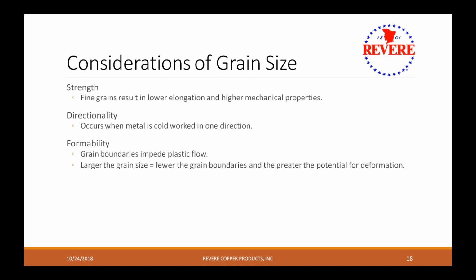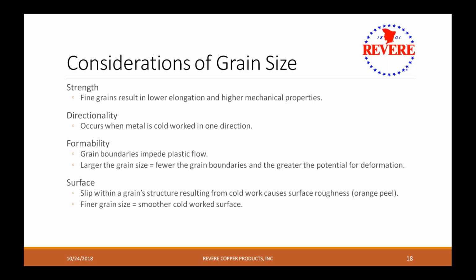And then finally, surface. So there's a condition called orange peel, and if you do a lot of cold work to metal prior to annealing, and then you anneal it to the point of a lot of large grain growth, large grain structure, you can get a surface that looks like orange peel. Whereas if you anneal it for a shorter amount of time or a lower temperature, you'll have a smoother surface. It'll give you more of a cold work looking surface if you have fine grains.